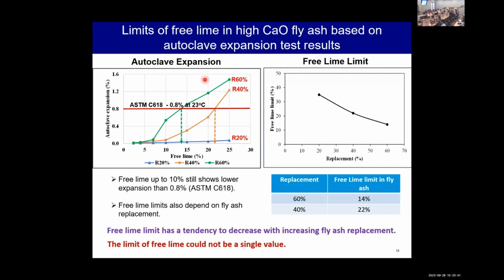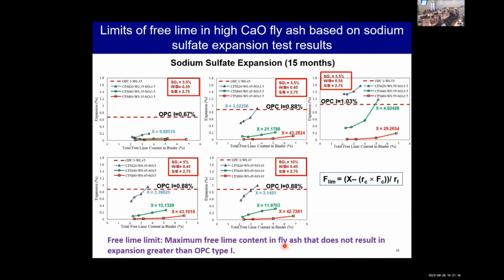In our recent research, we also studied how to obtain the limit of free lime in high calcium oxide fly ash based on autoclave and sodium sulfate expansion. From the result, we can see that free lime up to 10% still shows lower expansion than the standard limitation. And after we obtain the limit of free lime, we can see that the limit also depends on the fly ash replacement. So we can conclude that the limit of free lime should not be a single value.